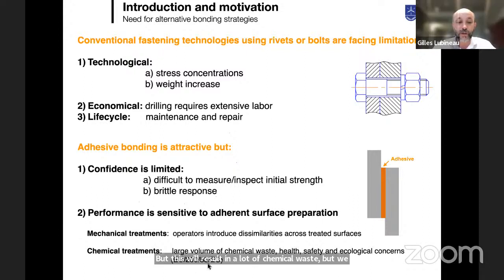That means it's difficult to measure and to inspect the initial response, the initial strength of such adhesive. Usually these are going to behave in a brittle way. The performance is very sensitive to the adherent surface preparation, meaning the way you prepare your substrate when you are doing the bonding. And this is usually made by using different types of mechanical treatment operators, but this is going to introduce dissimilarities across the treated interface, or chemical treatment, but this will result in a lot of chemical waste, and will also introduce health and safety concerns.